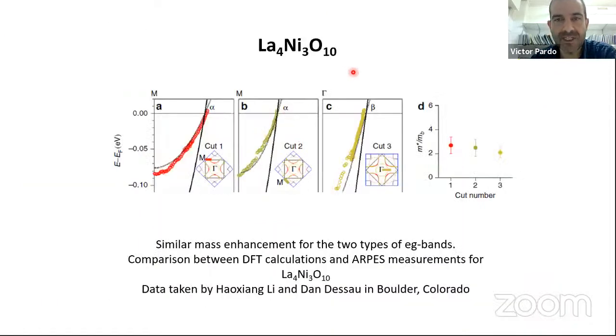This work is somewhat interesting for us doing DFT calculations, because we could compare what the DFT predictions were, how good they were compared to actual measurements of the band structures extracted from ARPES. And the calculations saw that the bands calculated are very good when compared to experiments, and you even have some mass enhancements that you can compare here. So for people doing calculations of correlations, this is a good indication of what the typical mass enhancements you would find in these nickelates.